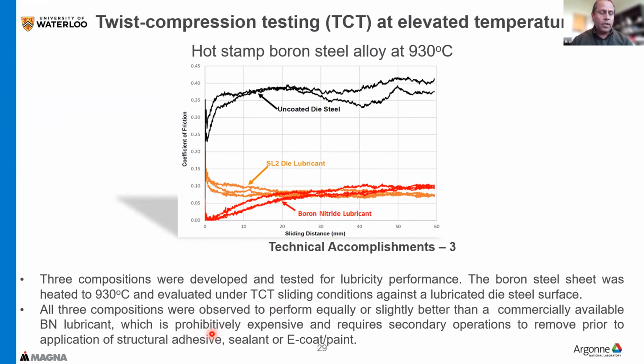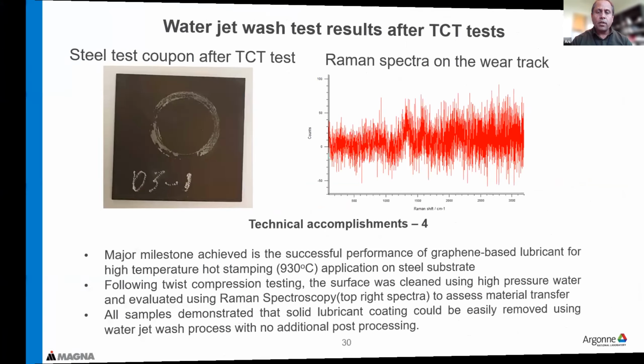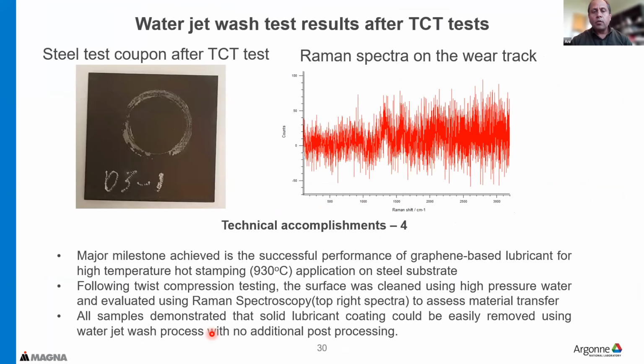Now, the other important thing that I already mentioned here is the availability, ease of removal. So in this case, just by water jet method, we are able to completely remove the lubricant, and this is the Raman spectra of this specimen without showing any signature of the graphene or other things on the surface. So basically, no post-processing required, just a simple water jet can remove all this lubricant very easily.